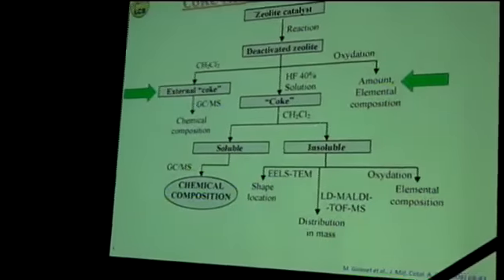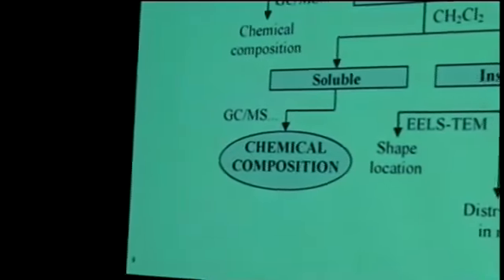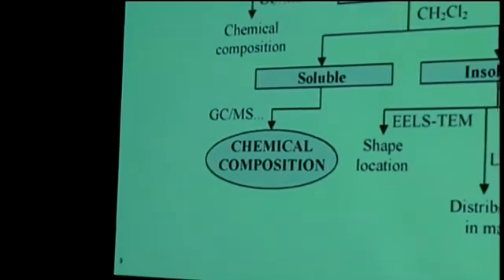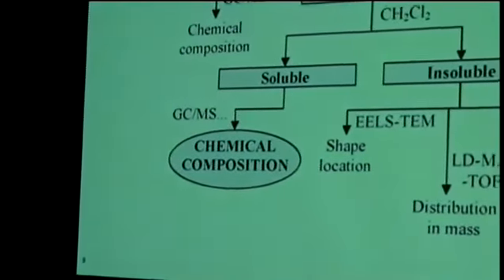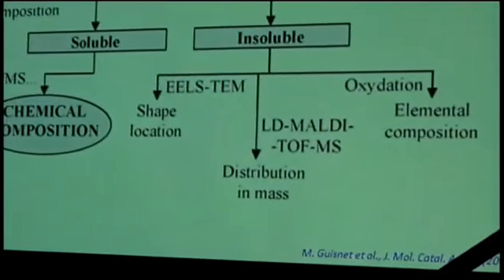In order to do that, you have basically to destroy the zeolite, and once you have destroyed the zeolite, you have now a solution, and this solution, you can have a part that is soluble in CH2Cl2, and this can be analyzed again by the same technique as here, which are, for instance, the GCMS, but any kind of analysis of a species in solution. And so it's a relatively straightforward thing to do.